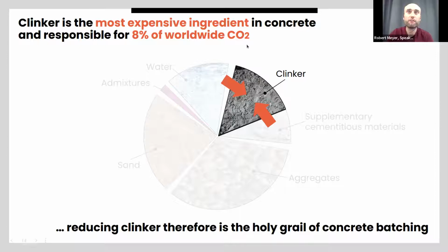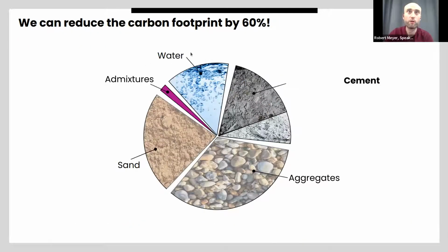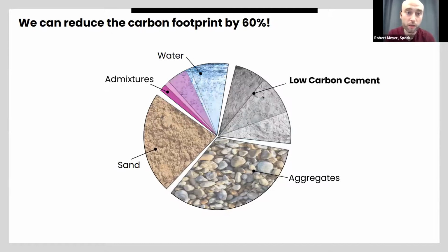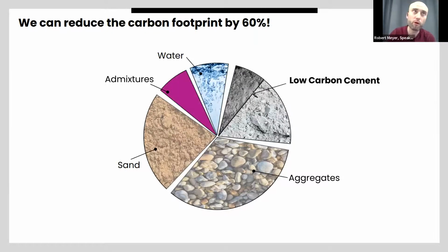So if this is regular concrete with regular cement, with lots of clinker and a high CO2 footprint, simply by replacing the clinker with, for instance, limestone flour and a bit more admixtures and plasticizers, we can actually reduce the carbon footprint by 60%. So then we have low carbon concrete made out of low carbon cement, simply by replacing the clinker with CO2-free filler material. That's a very powerful lever, because we can slash the footprint by around 60%. And that is not a pipe dream, because we've actually done it.